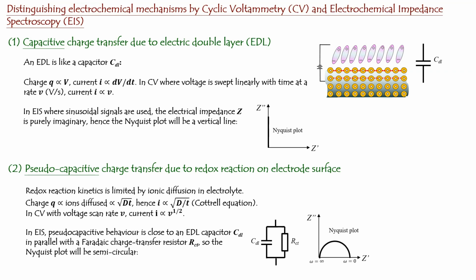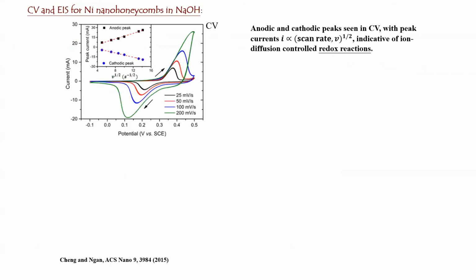While if you have the charge transfer mechanism, the charge is delivered by diffusion. So for diffusion, Q is proportional to the square root of Dt, where D is the diffusion coefficient. So if you have a constant voltage rate, okay, because of the t in here, the current will be proportional to the square root of the voltage rate. So one is linear, one is square root. So by these two, you can also distinguish between the two mechanisms. So for the first one, in here, when we have the redox, this peak for oxidation or that peak for the reduction, you measure the current and then you use different voltage rates, you would observe this square root dependence. So that already gives you a hint that this is due to the redox reaction.